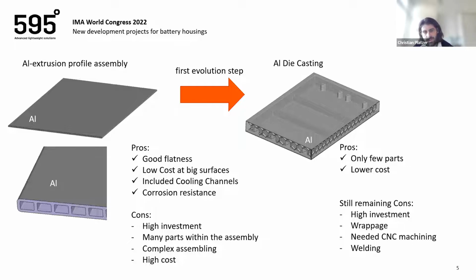And to assure a good heat transmission between the housing, which is the heat exchanger, for the battery cells, you need to have a very good contact surface, and you need to have a good contact. And therefore you need a good flatness. And this is something that extrusion profiles can provide you right away. And extrusion profiles are quite cost advantageous for big surfaces. And they have the advantage that they already can provide you with the needed cooling channels that are being used to control the temperature of the housing. You need to pump through some coolant, and with the profile, you have those channels right away from the production.